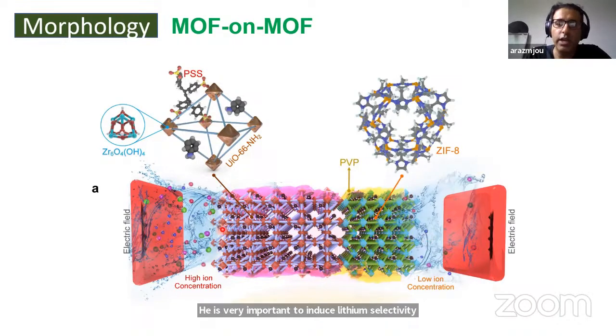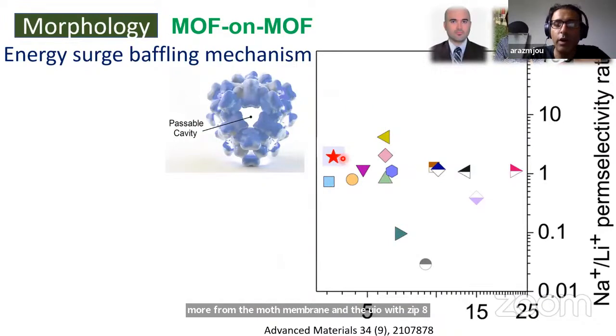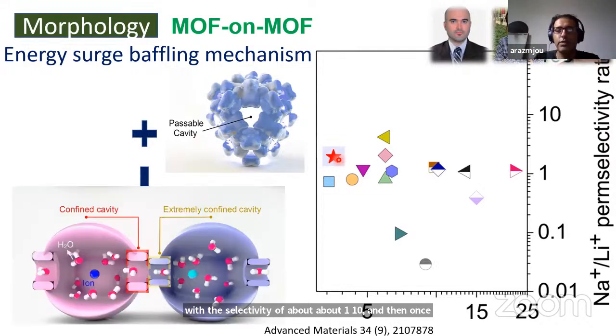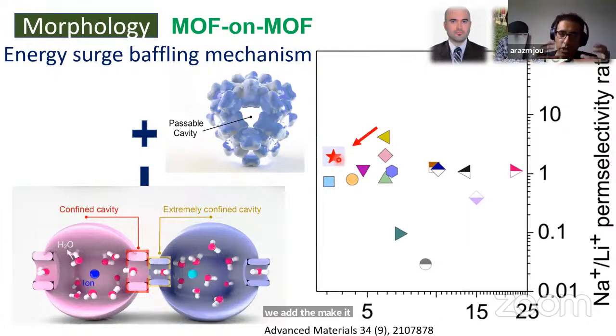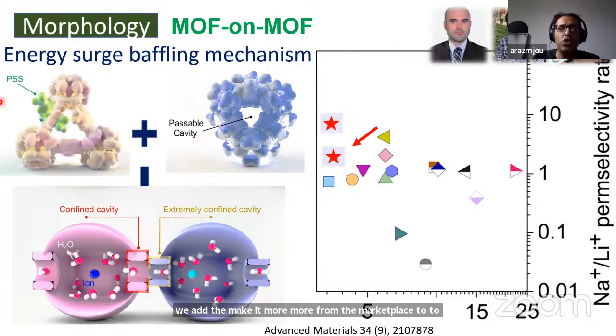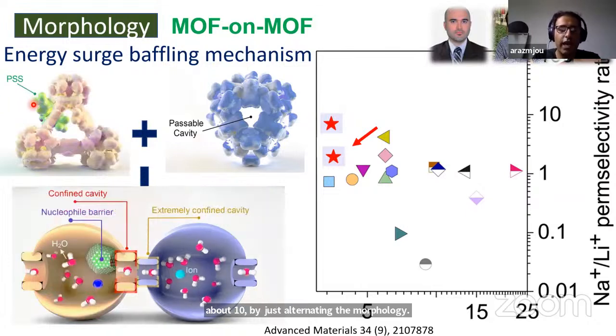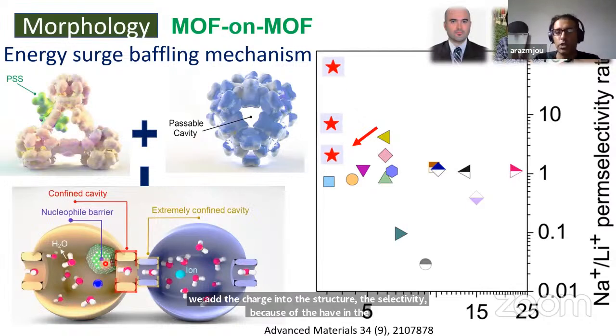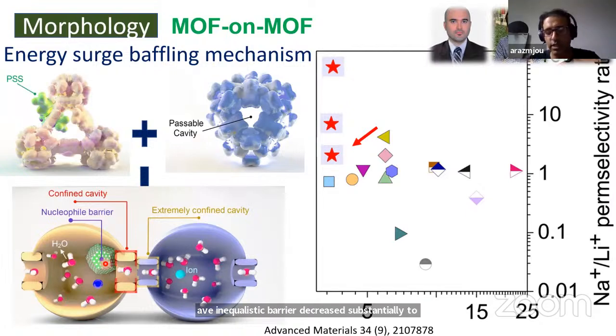We use a very complex structure, a MOF on the MOF membrane, UiO with a ZIF-8 membrane, and then we add the PSS charge. A typical MOF membrane has a selectivity of around 1 to 10. Once we make the MOF on the MOF membrane, the selectivity increases to about 10 by just altering the morphology. When we add the charge into the structure, because we have a nucleophilic barrier, the selectivity increases substantially to around 80, which is fantastic, because now we have a synergy between the asymmetry in chemistry and morphology.